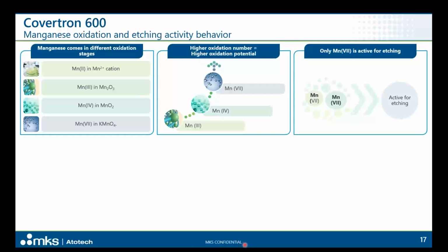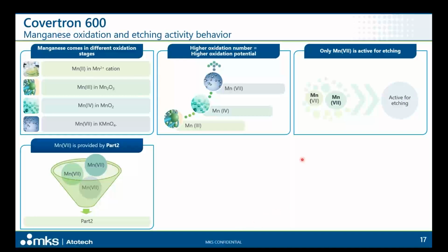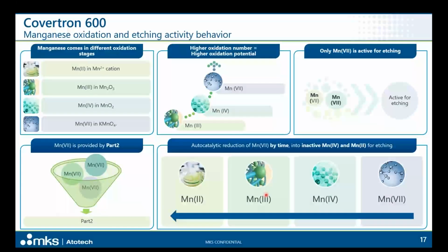So in Covertron 600, this permanganate, the active species for etching, is introduced through the Covertron 600 Part 2 additive. This manganese 7, depending on the working conditions, is not active for etching for a long time. What happens is that, over time, the manganese 7 breaks down as a result of an autocatalytic reduction reaction. So we move from manganese 7 to manganese 2, becoming, of course, inactive for the etching purposes that we require. And remember, this is an autocatalytic reaction driven by time that leads to these inactive species.